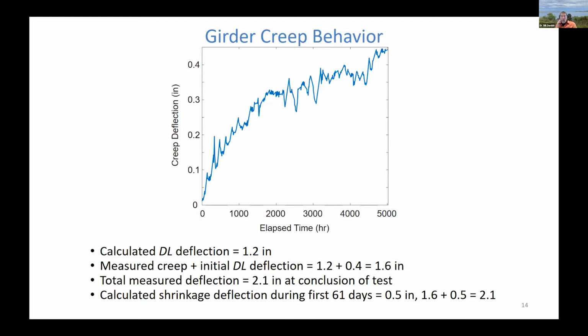So what we think actually happened is there's also some shrinkage deflection that occurred. During those first 61 days when that girder was fully supported, we can do a calculation. We can estimate what the shrinkage induced deflection would have been as the deck underwent AASHTO specified, standard concrete mix shrinkage. It would have been about 1/2 inch. And that deflection, when the girder was supported at the ends, would have been mobilized as that shrinkage strain was released. And we would have ended up at 2.1 inches, which is about the total we measured.